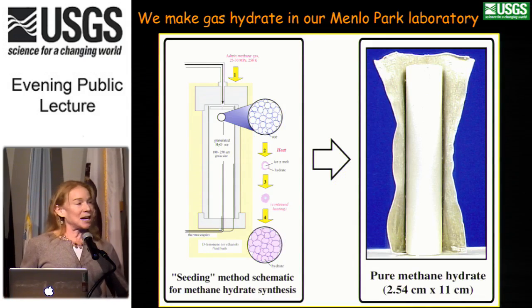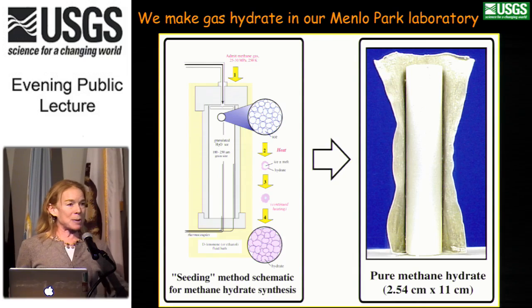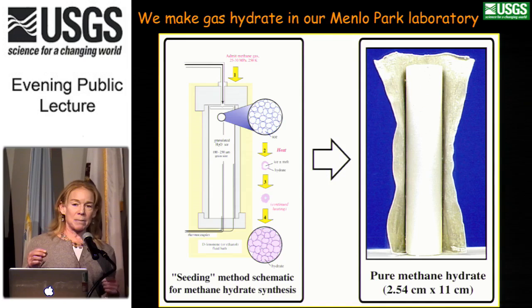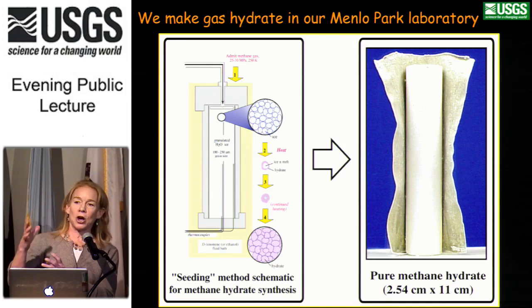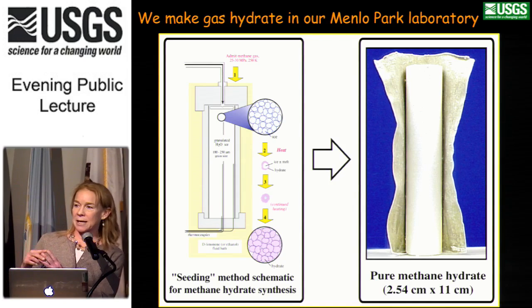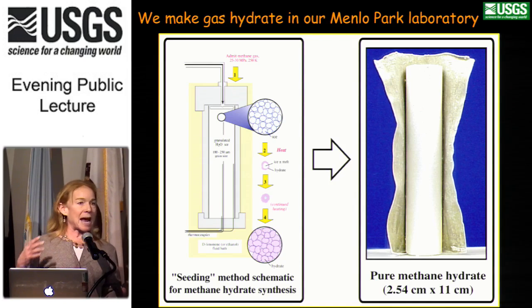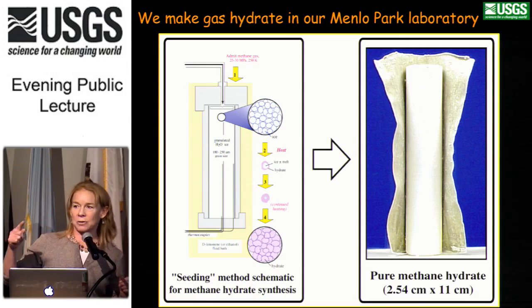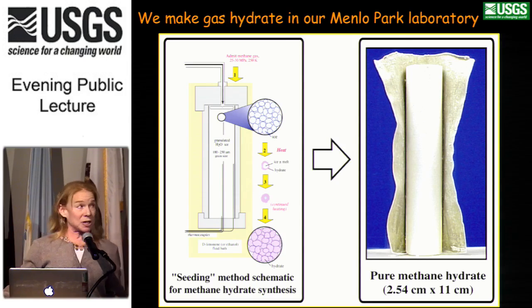So we make gas hydrates. My example I'm showing here is methane hydrate. We can make a number of different kinds of hydrates. We have special pressure vessels, and the technique that we developed was to make hydrate so that we can make the same type of sample over and over again that we use in physical property tests. That's an important aspect of a sample material, that you can make a sample and use it in strength tests or electrical conductivity tests, and you know what it is you're measuring because it has the same grain characteristics.